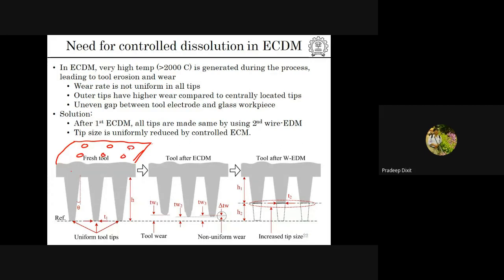If you recall the discussion today and yesterday, we are making this particular tool electrode by the EDM process, so all the tips have the same height. Now if you use the tool during the ECDM process, because of the high temperature, which goes beyond 2000 degrees Celsius, there's always going to be some tool wear. We have noticed that even the tool wear is not uniform or consistent. If you look at the profile of the tool electrode after the ECDM process, all the tips are not going to be of the same height, and this will create a problem.